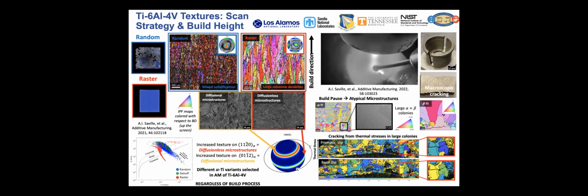And this was regardless of type of build process, whether it was powder bed or DED, directed energy deposition kinds of processes. So this suggests that the texture components in the as-built condition could be used to potentially qualify and certify the microstructural condition for Ti-6.4. Similarly, we did some larger length scale. This is a wire DED build that we did with Sandia National Laboratory that they provided for us. And here we actually see an atypical microstructure, these large alpha beta colonies at a build pause where we actually see cracking that was present in the build. This is again back calculating the beta Ti high temperature condition. And then we were able to rationalize the crack path propagation pathway based on the different slip systems that we have in Ti-6.4, which was pretty neat as well.